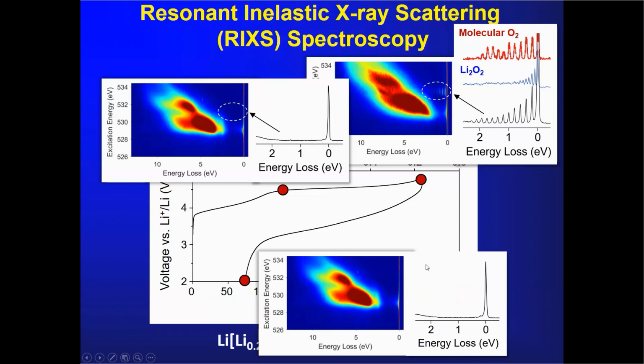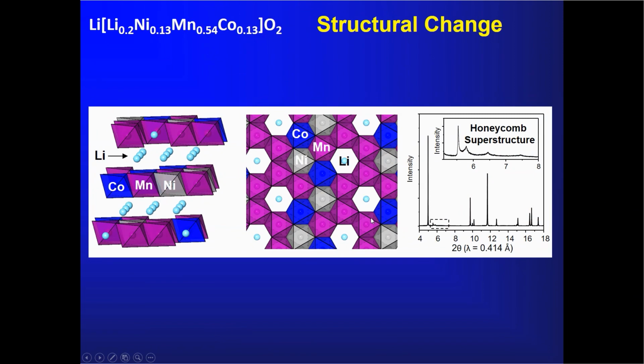So the take-home message, if you like, is that when you oxidize oxide ions, you actually form molecular oxygen that isn't molecular oxygen evolved from the surface. This is an ultra-high vacuum ex situ measurement, the RIXS. It's oxygen trapped in the lattice in the material. And it's a reversible process in the sense that you can re-reduce that oxygen back to oxide ions. And indeed, I don't know if I have it here. No, I don't. But you can go around the second cycle, and you can see oxygen formed again, and again back to oxide ions on discharge.